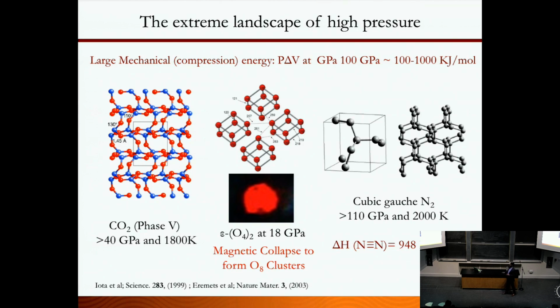If I give you an example of carbon dioxide, it's a gas at ambient conditions. But look at the periodic table, where you have SiO2. Why is CO2 not similar to SiO2? SiO2 is quartz, but CO2 is a gas. And on the other hand, nitrogen, why is it not similar to antimony or arsenic? The periodic table should be good for something. But if you apply pressure on carbon dioxide, it goes to a quartz-like structure, very similar to SiO2.